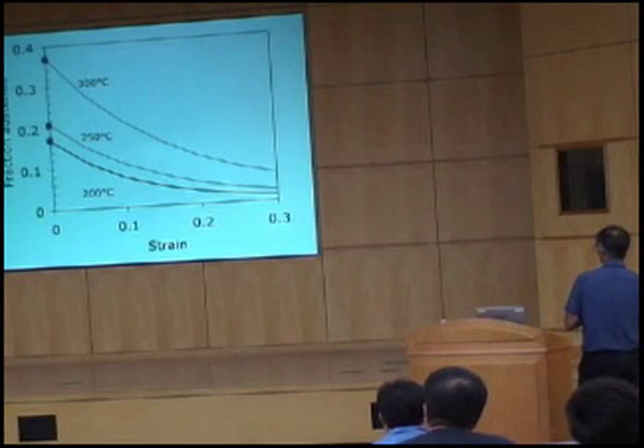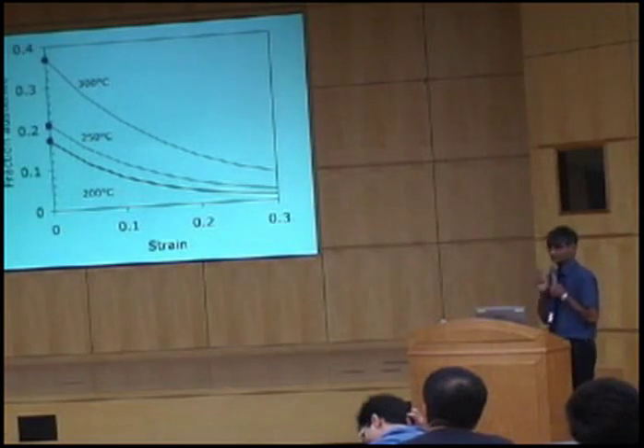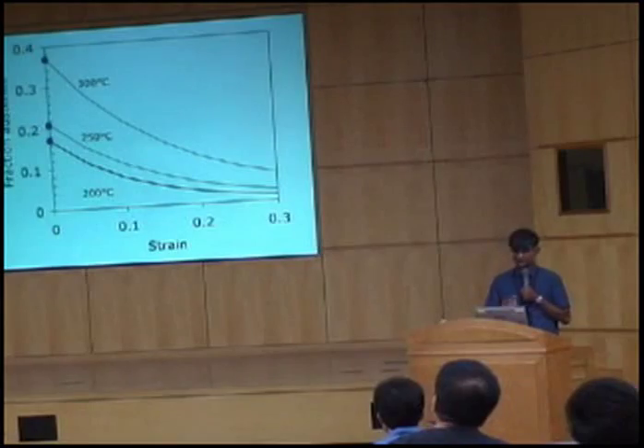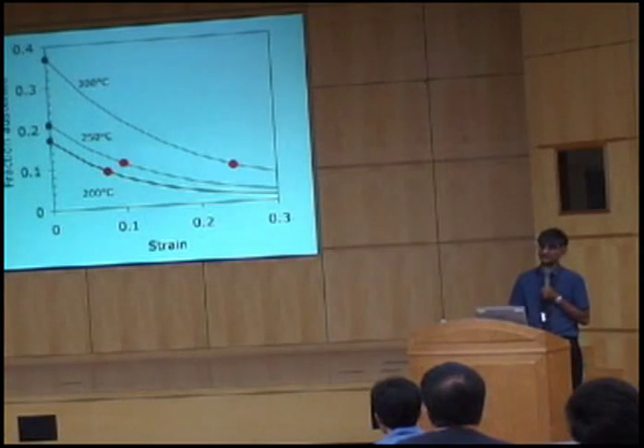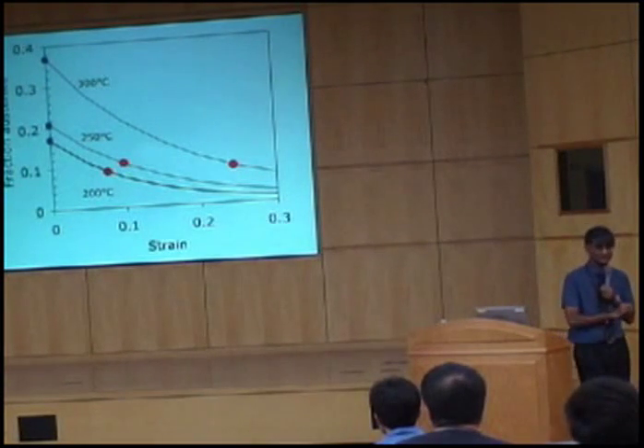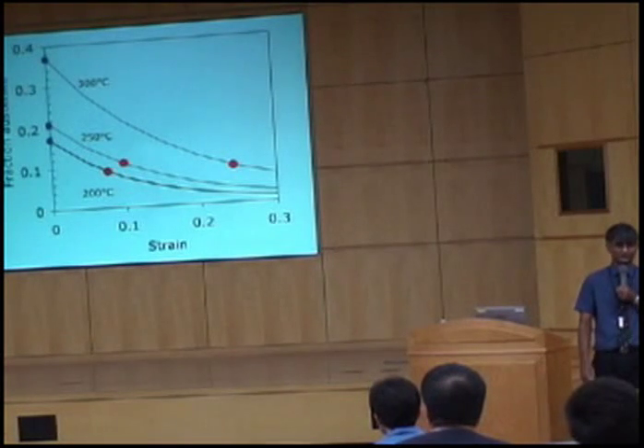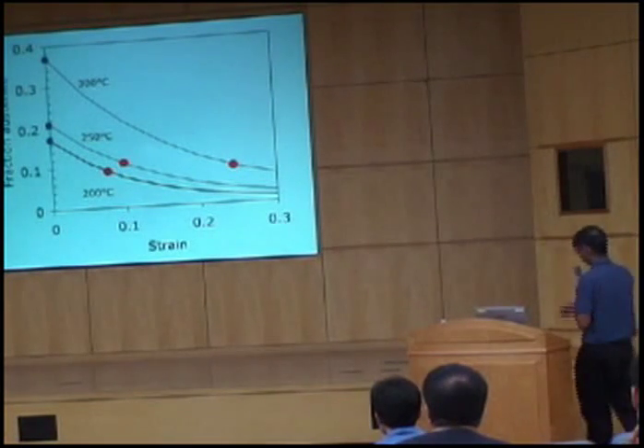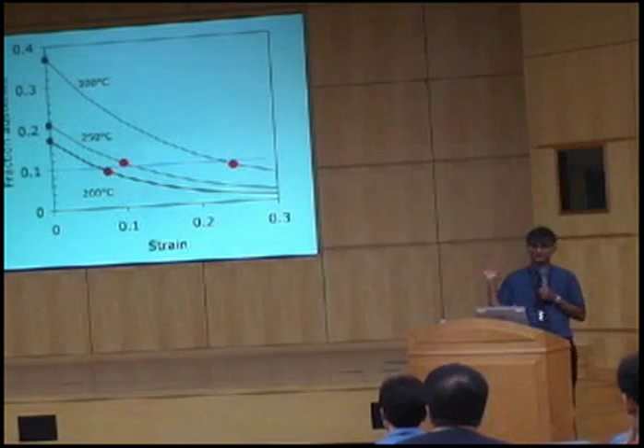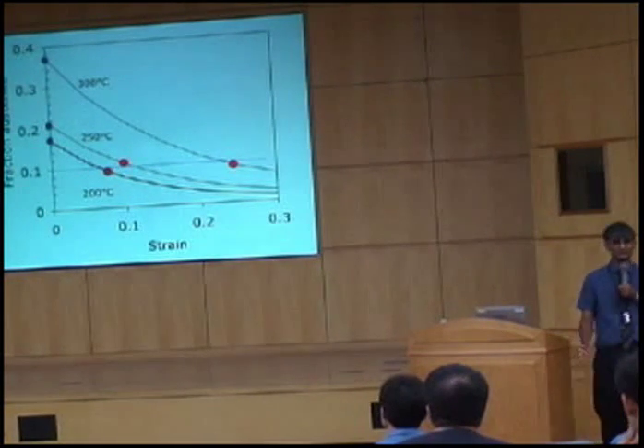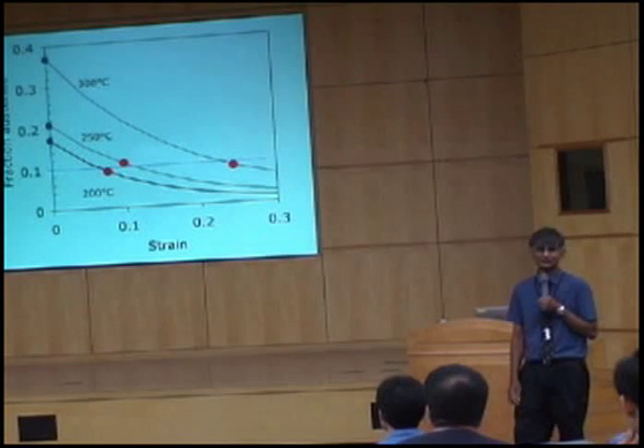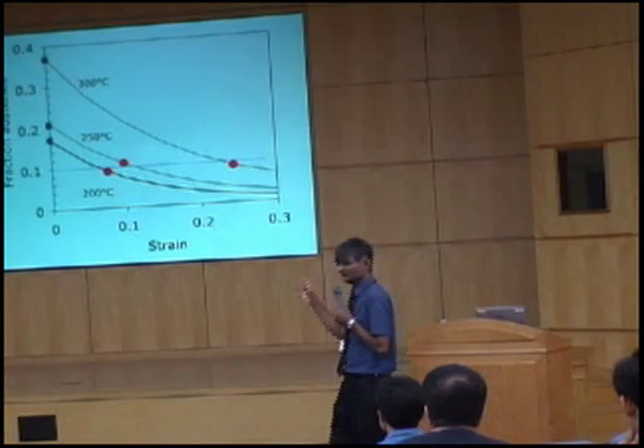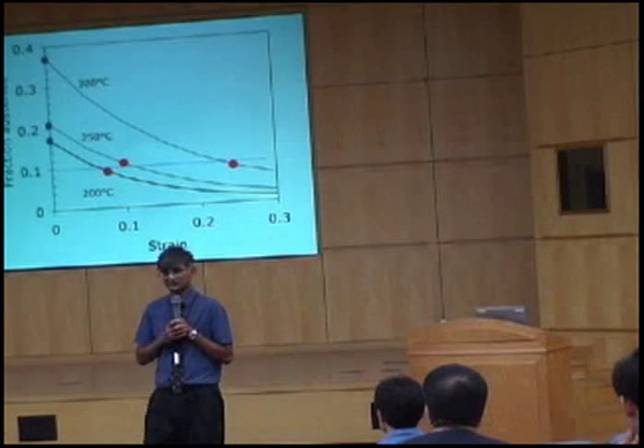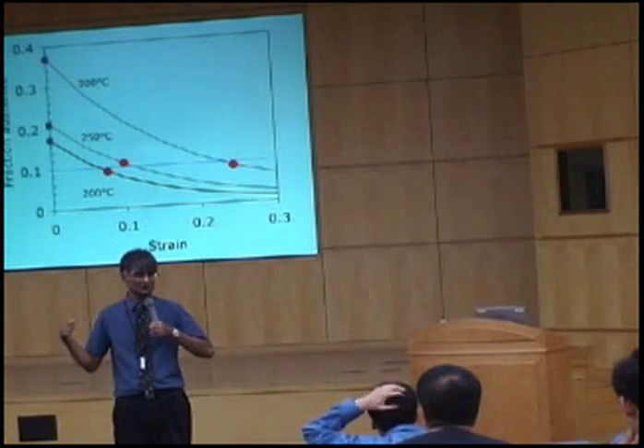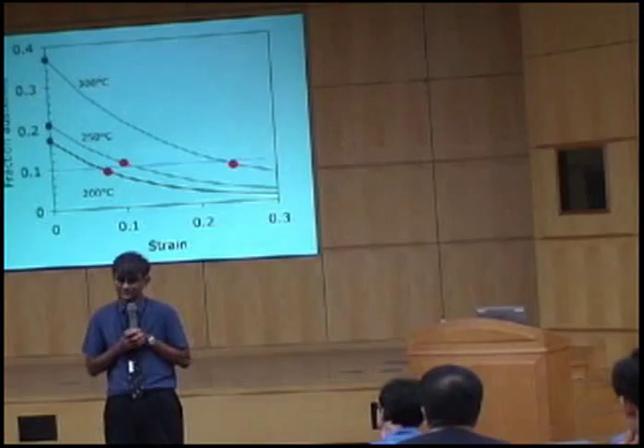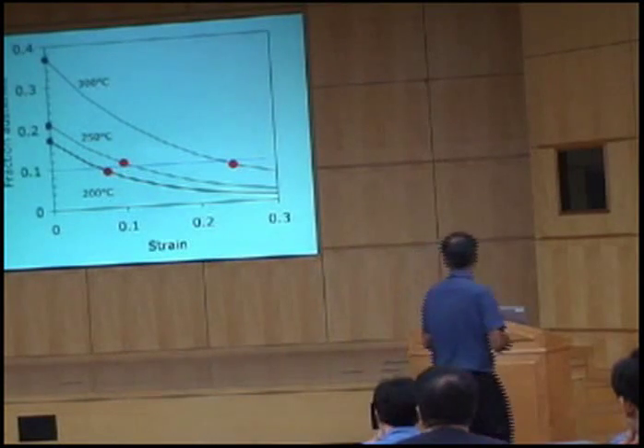And what I'm going to do is on these curves, I will plot the fracture strain, okay, for each of these samples. So here the red points are the points where the tensile specimen broke. And what I claim is that that's approximately when the austenite content reached 10% in the microstructure. So what I want to say is that there is this magic number of 10% of austenite at which the specimen breaks. Now, what is magic about this 10% of austenite?